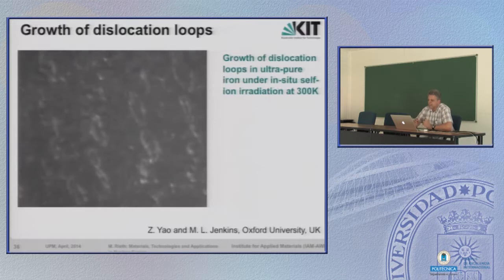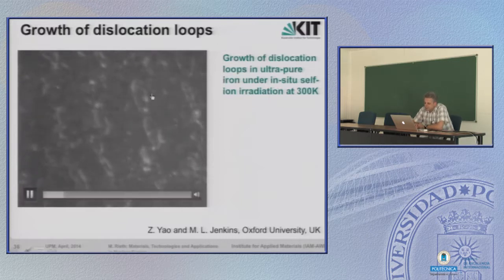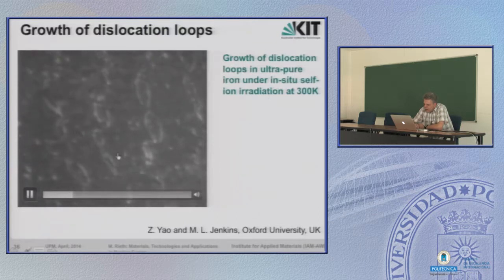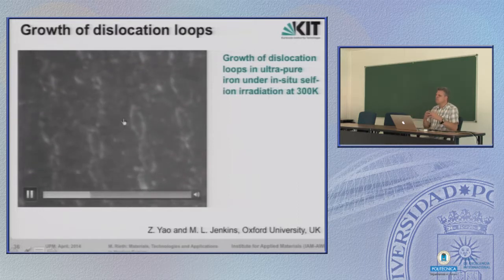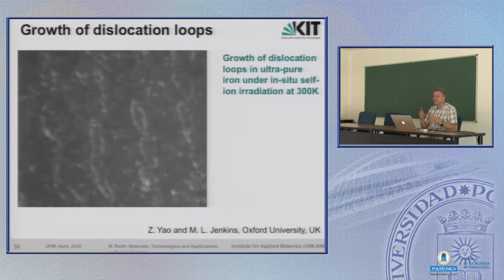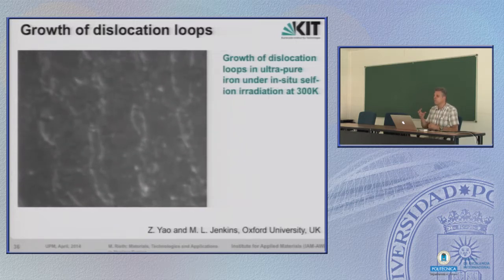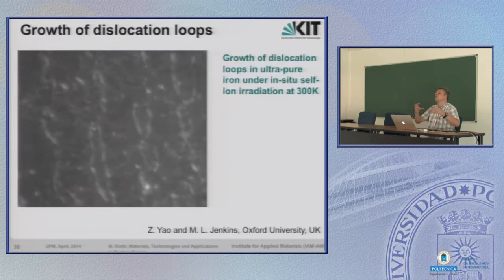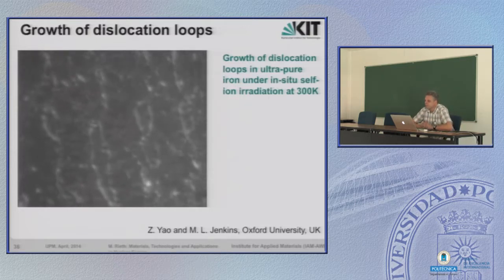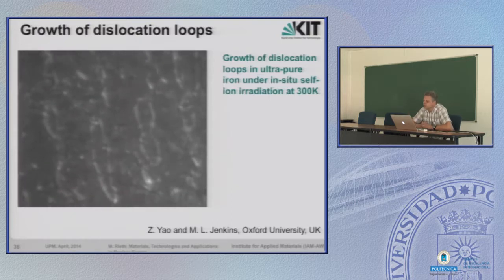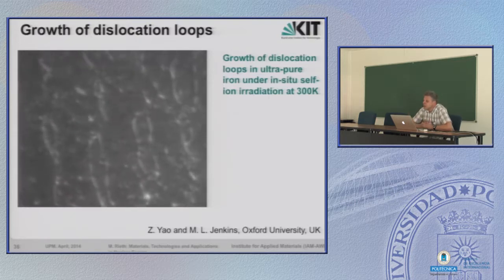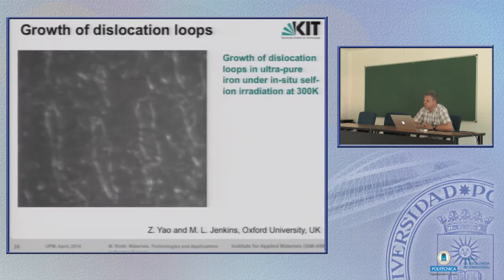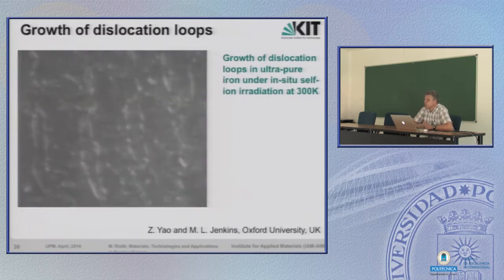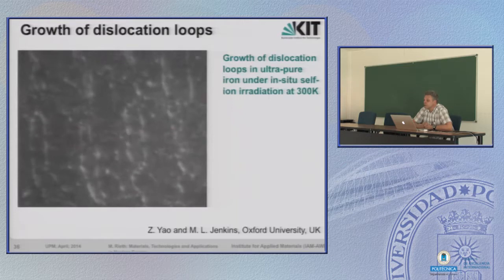Again, another study, in slower motion. Here, the dislocation loops are larger, they have already increased, and if you focus on those or those, you see they merge together with time. They interact with one another, and from formerly smaller single loops, they form a bigger, larger loop. This process goes on and on. So growth of dislocation loops, in this case in ultra pure iron irradiated at room temperature, is also a phenomenon.